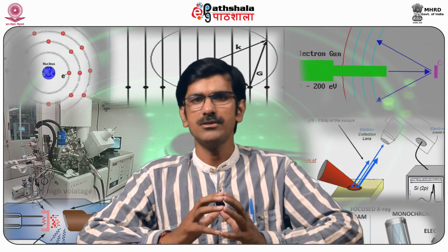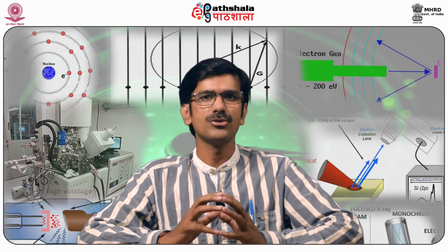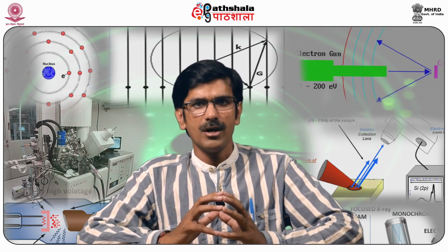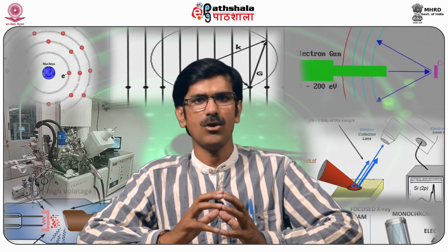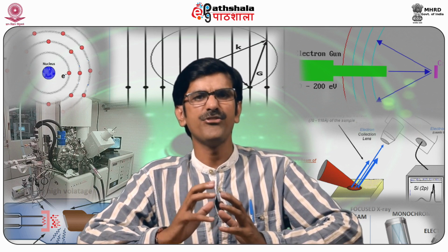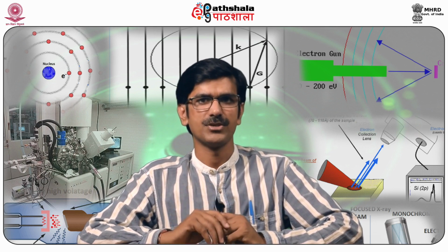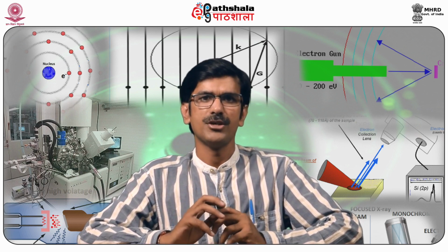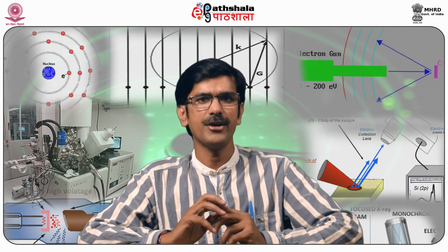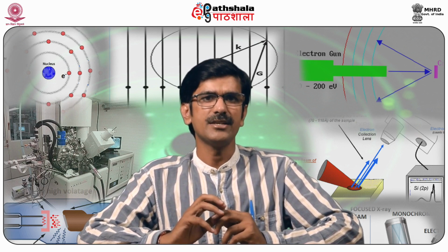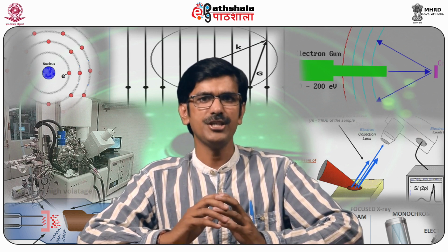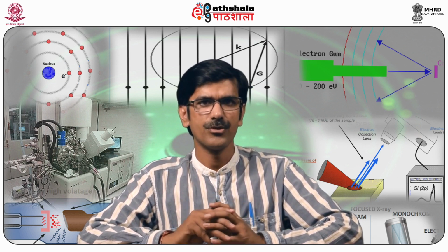The pore connectivity or the pore network also causes the loop. For example, if larger pores are accessible only through narrow pores, then the larger pores cannot be freed at the relative pressure corresponding to the capillary evaporation. It is because the narrow pores are still not vacant from the condensed adsorbate. Now we will discuss each type of hysteresis loop.